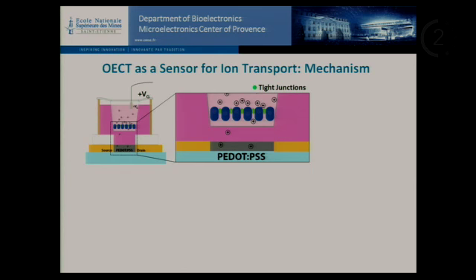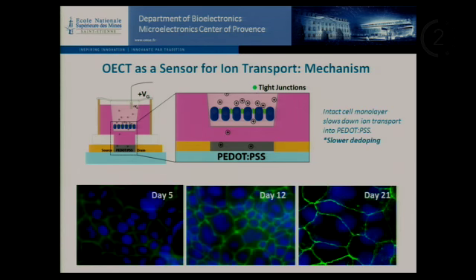So how do we use this to monitor cells? We have this organic electrochemical transistor here, and in between the polymer channel and the gate electrode, we culture a layer of cells on a porous cell culture membrane. After 3 weeks of culturing, they form a tight monolayer. Tight junction proteins are shown here in green and the cell nucleus in blue. When this layer is intact, when these cells are healthy, they form a barrier to ion transport.